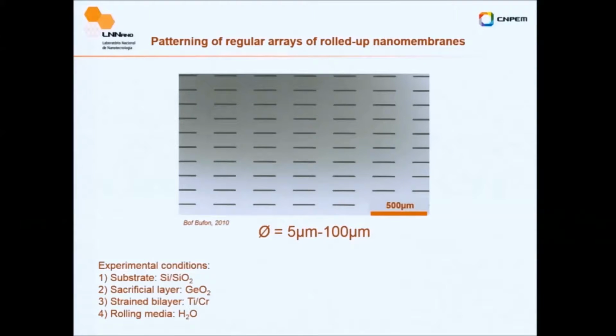In a typical case, this is an array of tubes. You can see on the surface that they are spaced. You can generate tubes from 5 microns to 100 microns and keep the tube shape. This is the experimental condition of this particular tube: substrate of silicon, silicon dioxide, sacrificial layer of germanium dioxide, titanium, chromium. One is compressed, the other has a tensile stress. When you remove this in water, the stress is released and the material curls.